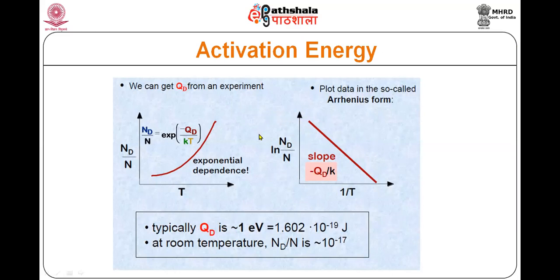The benefit is that the slope is nothing but minus QD upon K, where K is the Boltzmann constant. So with the help of the slope, you can find out the activation energy. If you have to get the activation energy of any system or defects, that's how you can calculate. You have to know how the defect concentration is increasing with respect to temperature. This can often be experimentally measured with the help of a technique called positron annihilation. That allows us to measure the defect concentration with respect to temperature, and you can then find out the activation energy.